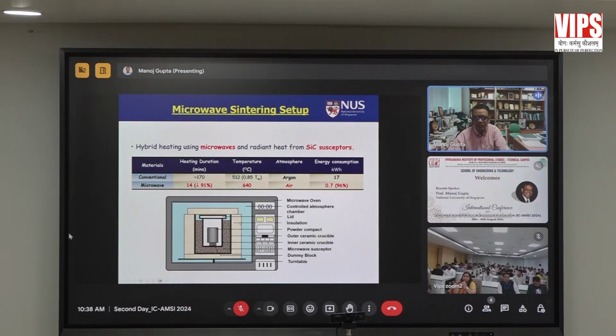And what we did was to create this inner, I will say, reactor chamber here. So we take an outer crucible here, an inner crucible here. In between, we put silicon carbide as a susceptor. We took the metallic ingot, pretty good in size, 35 in diameter and about 40 in length, and we just